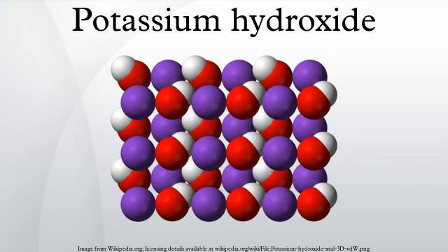Structure: At higher temperatures, solid KOH crystallizes in the NaCl crystal structure. The OH group is either rapidly or randomly disordered so that the OH group is effectively a spherical anion of radius 1.53 Å. At room temperature, the OH groups are ordered and the environment about the K+ centers is distorted, with K+...OH distances ranging from 2.69 to 3.15 Å, depending on the orientation of the OH group.